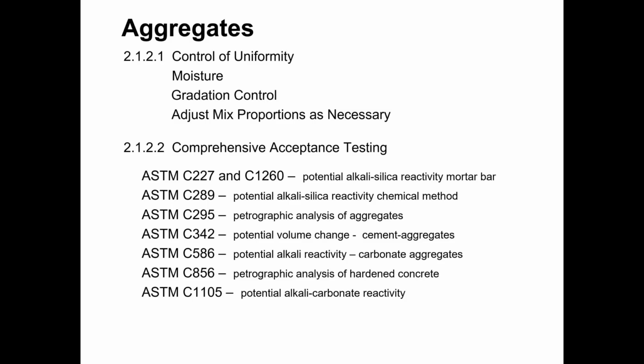We also want to have gradation control. We want our aggregates to be consistent in gradation from one shipment to the next. We should be doing regular gradation testing at the plant. PCI requires that for most plants that they do a gradation test for a given aggregate at least once per week. If the aggregate is in heavy use, you may have to do more frequent testing.